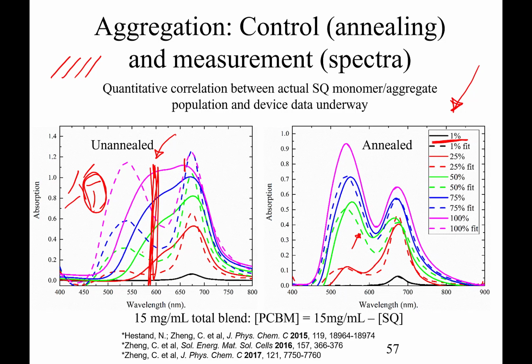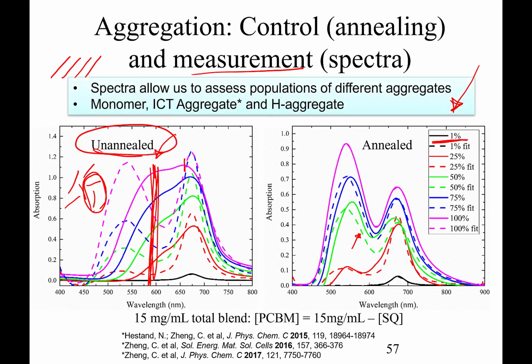So the point here is with annealing, we can control the packing of the materials, and we in principle can measure the presence of the aggregates and the monomers. We get a pretty poor fit of the unannealed materials, but we can start to quantify these things. We also label these things in different ways. This double hump in here, I'm not going to go into this right now, but we know that this is associated with an intermolecular charge transfer aggregate.